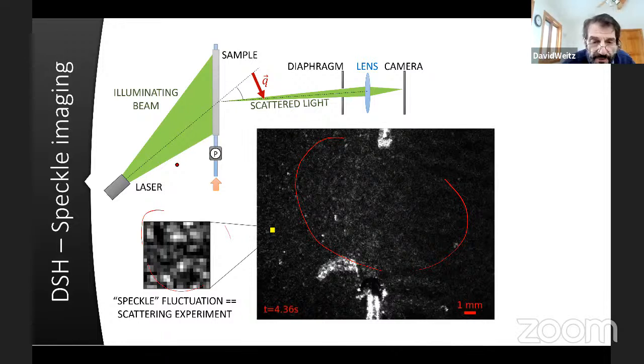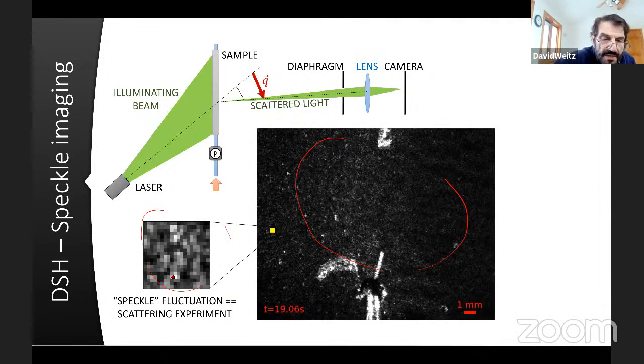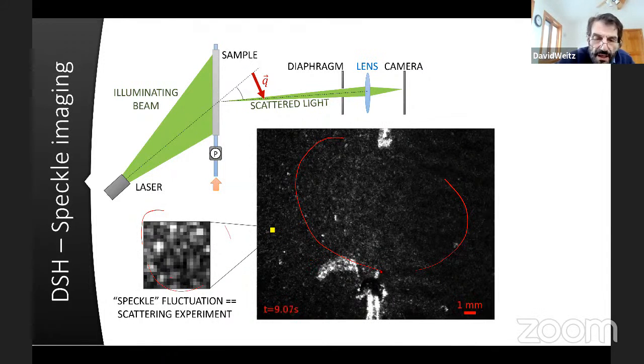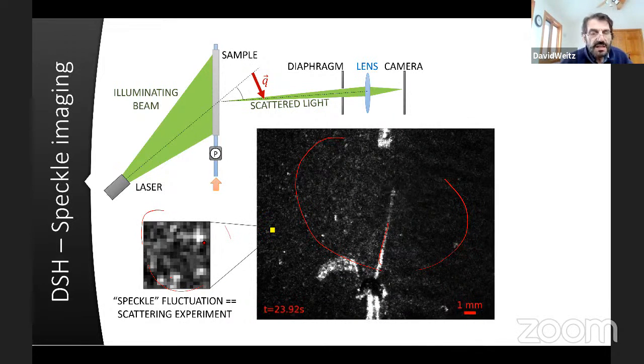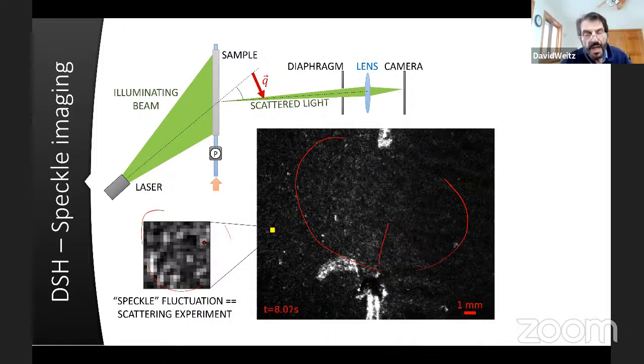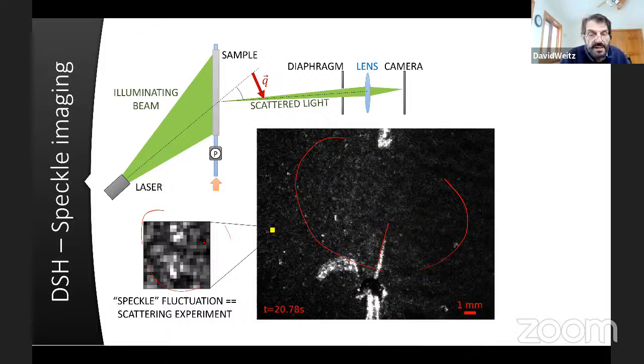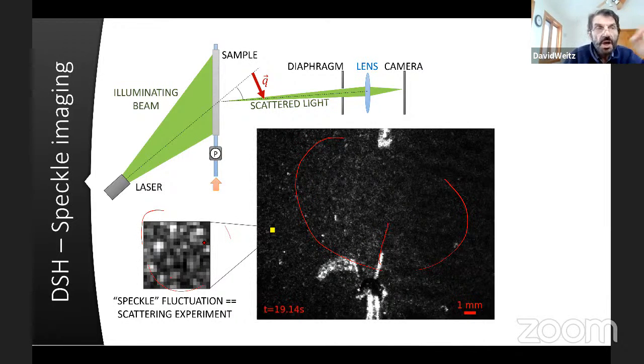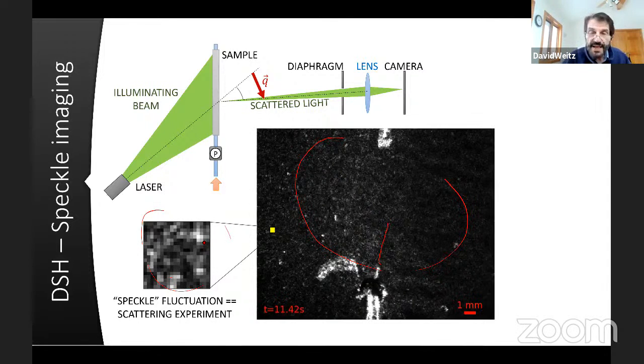Let me see, I think if I play this, yeah, you can see the fluctuations of the speckles. That means they're moving. This is looking over here, way far away. Here's the crack moving here, way far away. You can see that the speckles are still fluctuating. So you're still seeing motion because it's a solid. You see it not from the motion of the speckles, which is what we were seeing before, but rather from the fluctuations in the intensity.